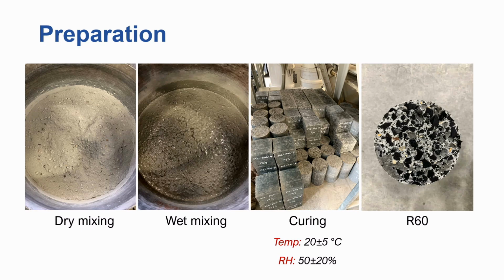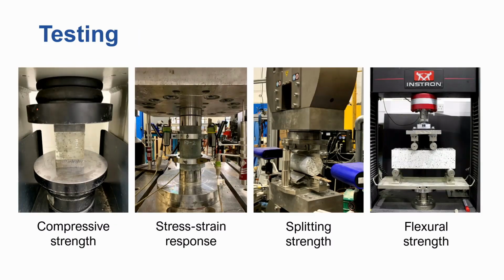This is just a photo, a cross-section of one of the cylinders, the R60, with the R60 concrete having the largest rubber content. Just shows the dispersion of rubber throughout the cross-section. Then we initially tested those for the fundamental mechanical properties, including the compressive strength, the stress-strain response, the splitting tensile strength, and the flexural strength.